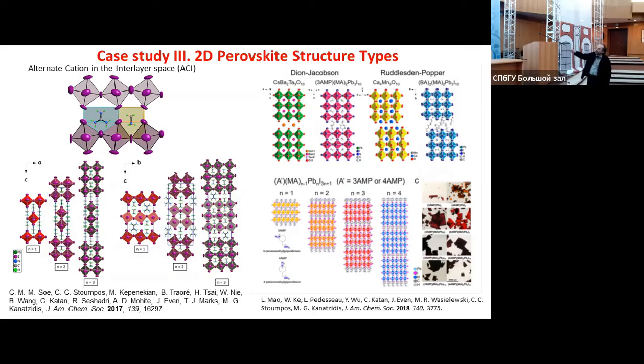And this is also this strange combination where you use two cations in the layer, and they fill different pockets. This is alternating cation in the interlayer space. Not the most brilliant name, but it describes the situation. And this one, together with this one, bring the layers closer together. And this is the search for two-dimensional perovskites that have actual communication between the layers. So we want to break the infinite well.